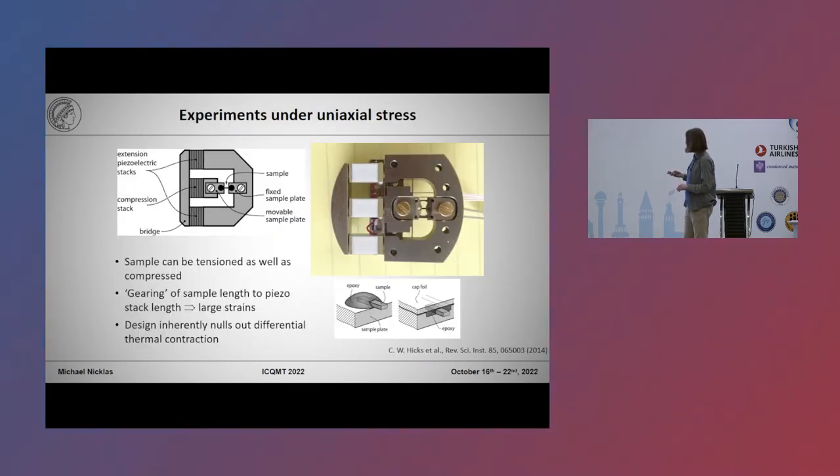Let me show you what we did here. We had this uniaxial strain device which was developed by Clifford Hicks and we have here three piezo stacks. In this design, basically when you apply a positive voltage to them these are expanding and this one here is compressing. And in that sense when you cool down the device you compensate for the thermal contraction so you don't break the sample just by cooling down. And what is also nice in this device: the sample is much shorter than the piezo stack so you have a gearing effect and can apply much larger strain than when you would just glue the sample on the piezo stack what was done before.